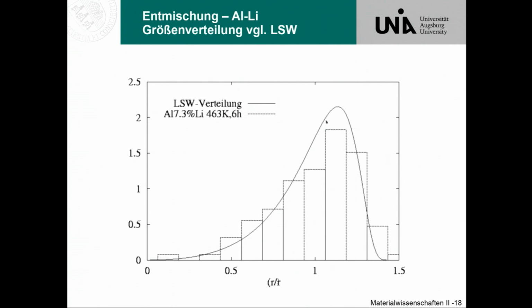And here, this is just this graph of the LSW distribution. And there's no parameters, nothing fit. It's just normalized to this average size here. LSW itself is derived assuming vanishing precipitate volume fraction and things. And no overlapping of diffusion fields and so on. There's a lot of assumptions behind, and I will show examples.